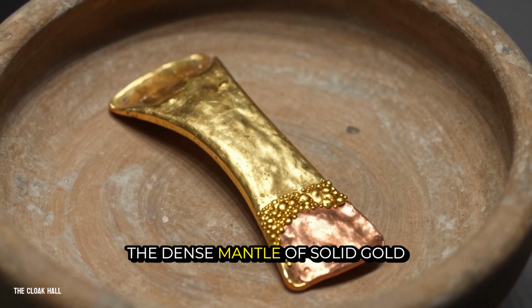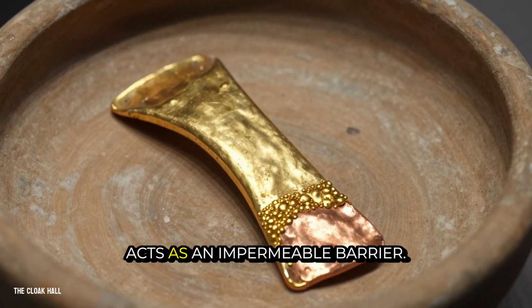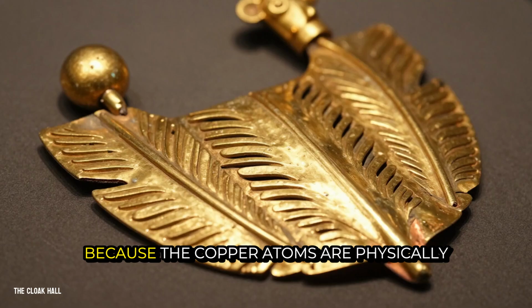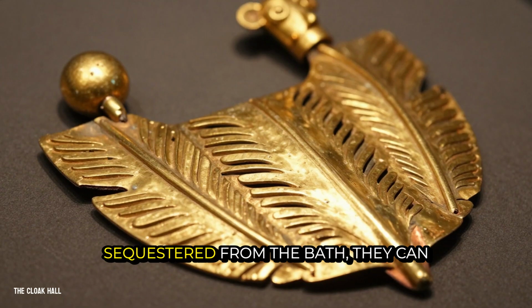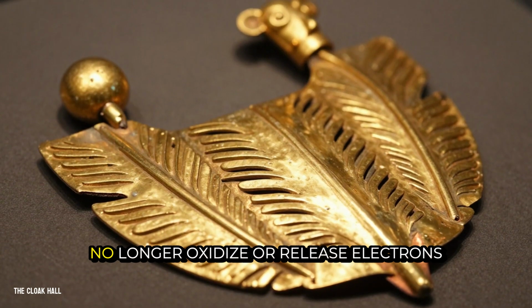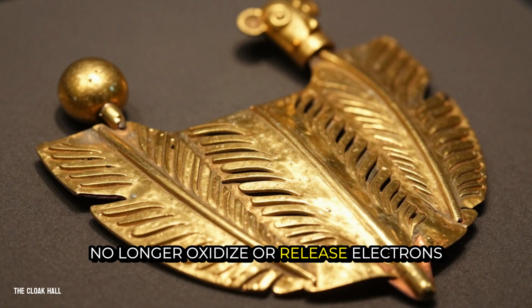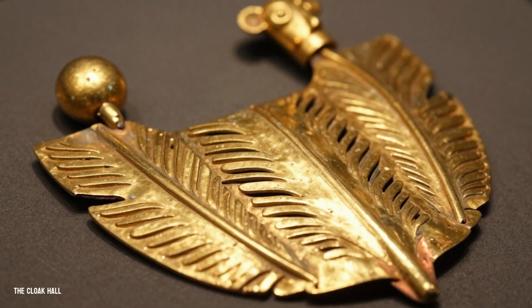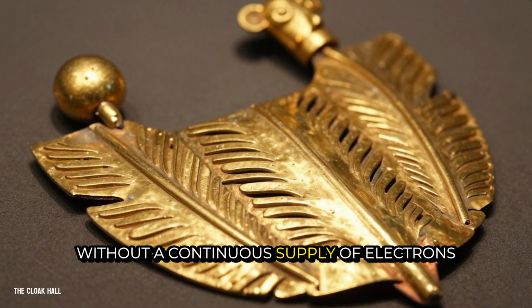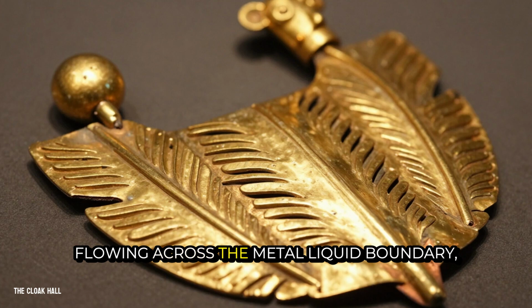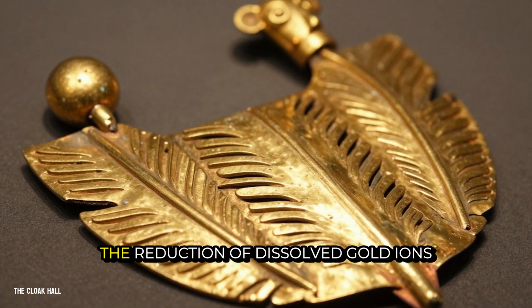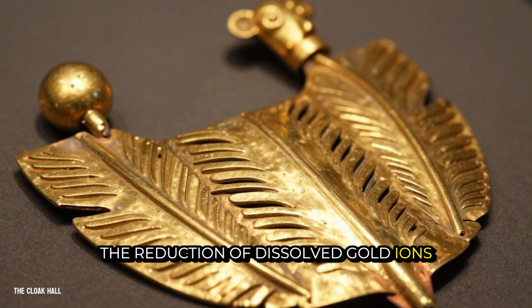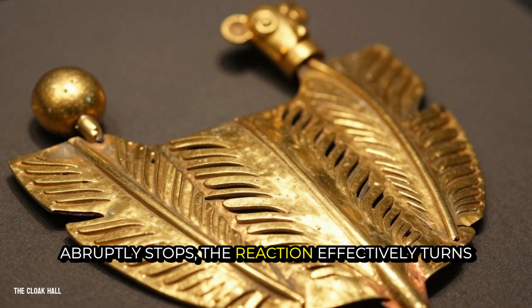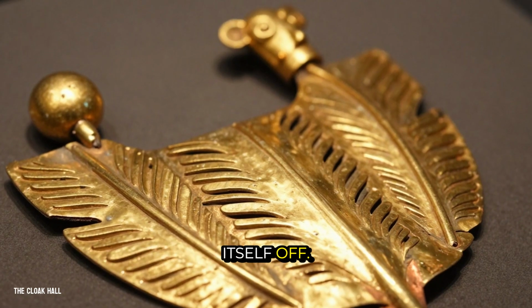The dense mantle of solid gold acts as an impermeable barrier. Because the copper atoms are physically sequestered from the bath, they can no longer oxidize or release electrons into the solution. Without a continuous supply of electrons flowing across the metal-liquid boundary, the reduction of dissolved gold ions abruptly stops. The reaction effectively turns itself off.